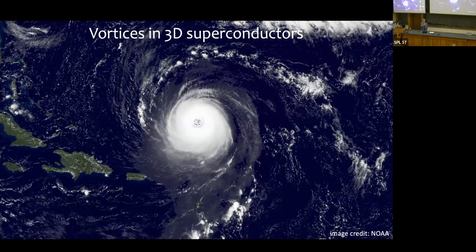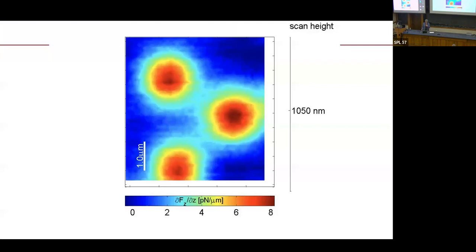You would have current swirling around the center. You would expect to see one of these magnetic flux tubes. And that's indeed what you see. This is an image of three vortices in yttrium barium copper oxide. This image was taken with a magnetic force microscope, that doesn't matter, a micron above the surface of the sample. And you can see these three big blobs of magnetic flux.